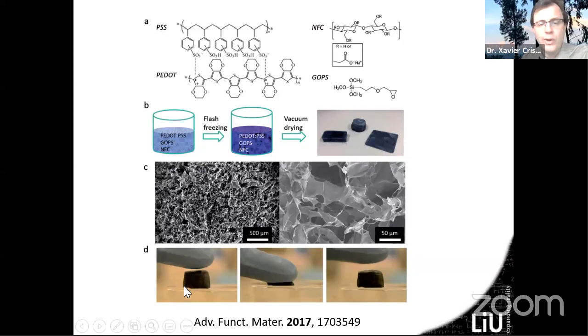And the feature we succeed to have is that it is to some extent elastic. So when you press with your finger on this kind of material, it recovers its shape afterward. If you try to do that with just conducting polymer, it just breaks apart. If you do that with cellulose, it's not going to come back very much. So there is a combination of materials of interest here.